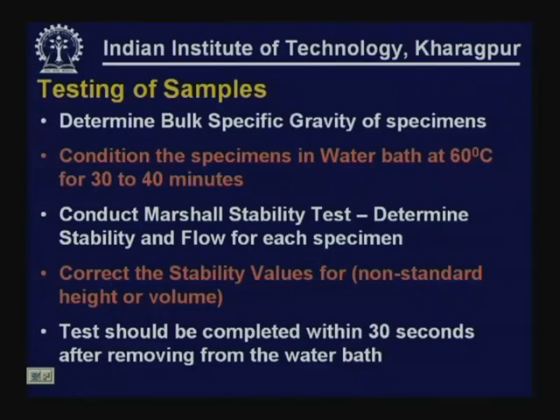Stability values must be corrected for non-standard height or volume. The standard specimen is 4 inches in diameter with a height of 2.5 inches; if the height varies, the volume differs and a correction factor must be applied. The test should be completed within 30 seconds after removing the specimen from the water bath, to ensure the temperature does not fall significantly below 60°C.